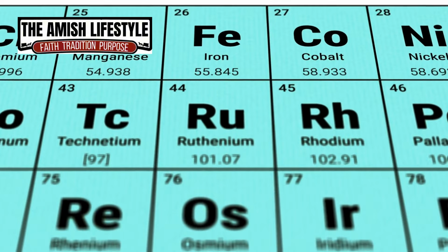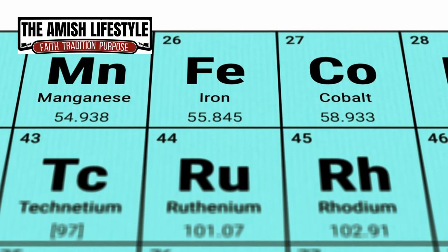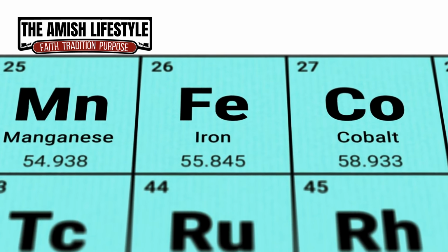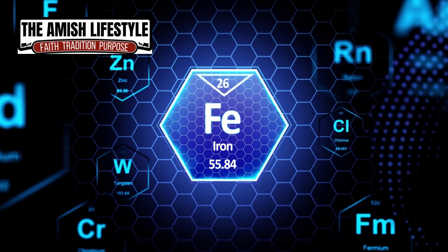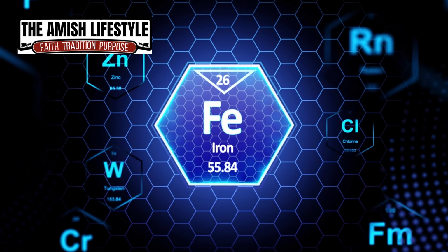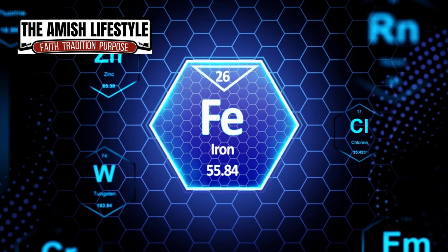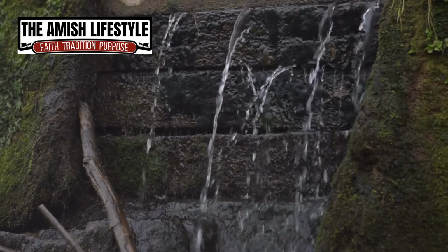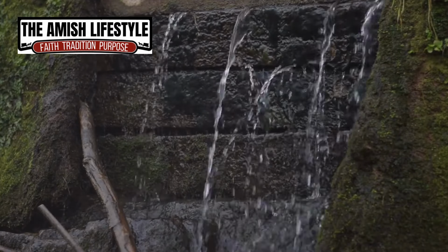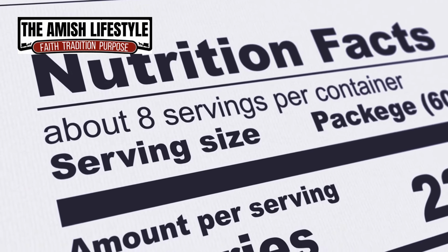And when that iron rich in phosphorus progressively rusted over the years, something amazing happened. The phosphorus helped build a thick, stable layer of protective oxides on the surface. This layer kept moisture and oxygen from getting to the metal, which slowed the rusting process by a lot. This was a fortuitous accident, an impurity in the ore that was good for it. The smiths didn't know why bog iron worked better, they just knew it worked.